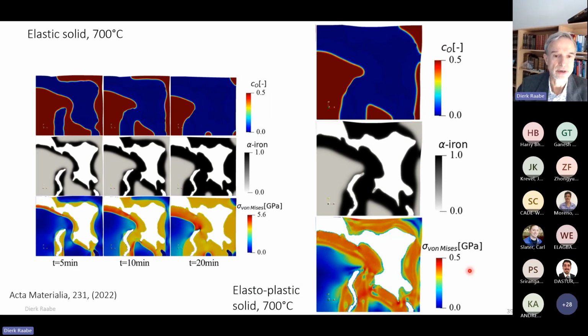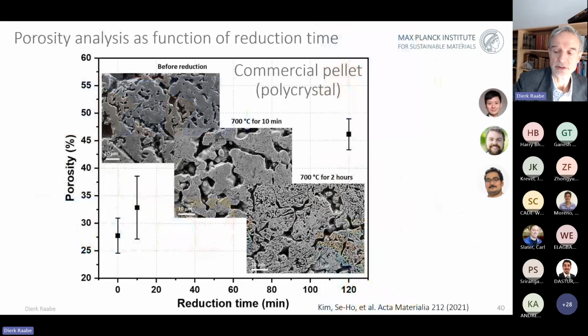And then you can reach stresses of about 0.5 gigapascal in the oxides and in the iron also, and that is much more realistic. It also helps you to make predictions about the dislocation content, because that is a feature that might be very important for discussing the role of dislocations, for instance, for the mass transport of oxygen or also of iron. So the knowledge about defects like free surfaces, cracks, and dislocations is very important, and that's why we are doing these types of simulations.